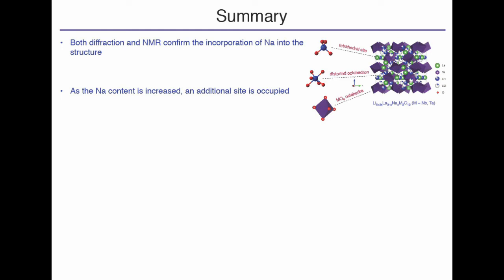Okay, so what do we think is happening in this system? Well, we think that initially when you substitute sodium into the structure, you do get substitution onto that lanthanum site, as predicted. But what we think then happens is that site fills up and some of the sodium goes onto the lithium site. In that case, you're then directly blocking the pathways for lithium to move. So you get a slight enhancement in the niobium case at the 0.2, but as soon as you hit the 0.4, you've blocked some of the pathways. So it's clearly a size issue.